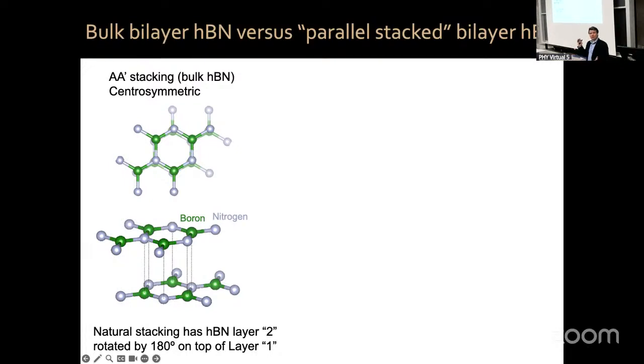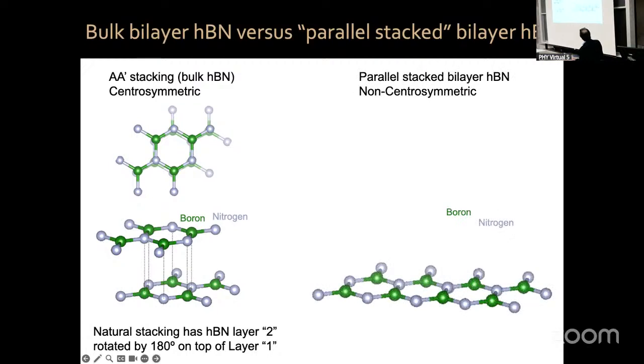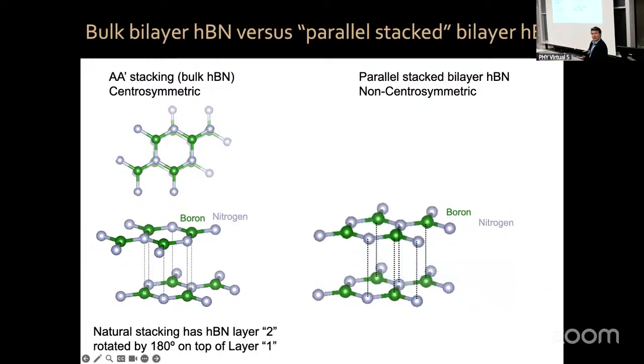Since we can put two materials on top of each other at any angle we want, we can take a monolayer of hBN, single layer, one atom thick, cut it, and place it on top of itself at 0 degrees instead of 180 degrees as the natural crystal wants. This is called parallel-stacked bilayer boron nitride.